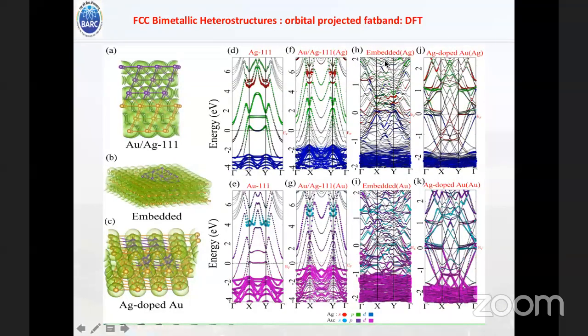So there will be a corresponding reduction of the carrier effective mass. But if you are going for the embedded and doped systems, you can see here there is some kind of localization of the carrier which is happening for a certain part of the Brillouin zone, and you can see from X to Y there is a kind of carrier localization here. And for this Ag-doped Au surface, in fact there is a localization here, and also there is a band inversion here. So with a small amount of fluctuation within the system, you will be able to open a gap here, and there can be a flat band kind of more effective mass carrier localization present in the system.